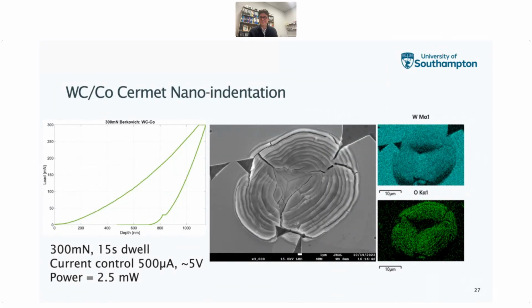And so when we start indenting on something like the tungsten carbide phase, even if we're going in quite deep here, we put a 300 millinewton load into this particular grain, and so we're in quite far, and then we've tried to keep it at this 2.5 milliwatts, and you can see that the oxidation has proceeded subsequently, radiating outward laterally. And quite interesting, this doesn't really push the tip back out so much, because I think tungsten trioxide is a little bit softer than the cobalt oxide that we were forming there, and so it continues to penetrate in. And so it's a good way of destroying your hard carbide grains by forming a surface oxide on it. And you can see the cracking as the brittle phase is cooled from the surface. You just have a surface oxide here.